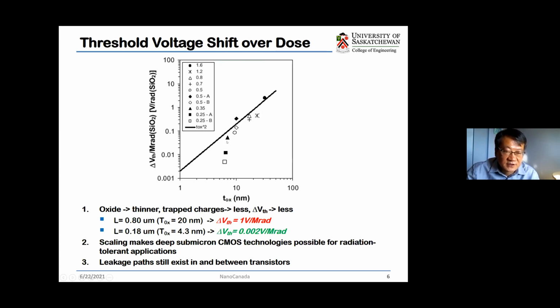So the effect actually is dominated by the gate oxide. For example, here in the diagram is the gate oxide thickness, and this is the threshold voltage shift over the dose. We use 1 unit megarad. Actually, it's a larger unit, but we can say that when the gate length is 0.8 micron, this kind of technology has an oxide of 20 nanometers, and then the threshold voltage shift is 1 volt per megarad. So it's a larger voltage shift, right? And then at 0.18 micron, the oxide thickness is 4.3 nanometers. The threshold shift is very small, only 2 millivolts per megarad.